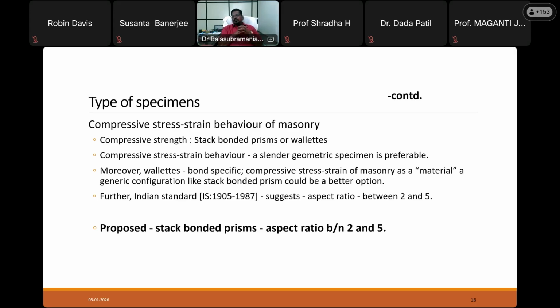The present code 1905 suggests this stack bond prism. Stack bond prism means we are laying one brick above the other with mortar in between. So a 5 brick stack bond prism means 5 bricks will be there. In between there will be 4 mortar interfaces, and the top and bottom faces will have a very rich mortar capping. The aspect ratio, which is the height to least lateral dimension ratio, is 2 to 5. That is what the code suggests.